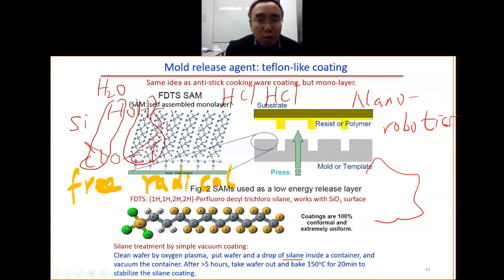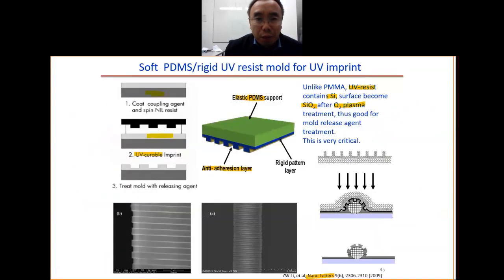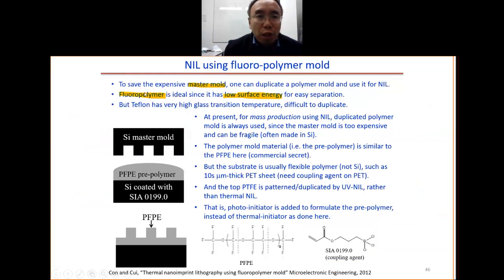So ideally, we want the mold to have low surface energy, then we do not need this self-assembled monolayer. This way, we can use the mold hundreds or even thousands of times. So this is the idea here. We have the mold in fluoropolymer. You can see this one. It is fluoropolymer, so this gives you low surface energy.